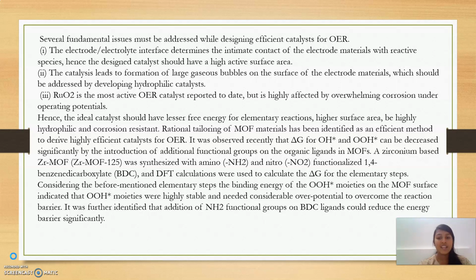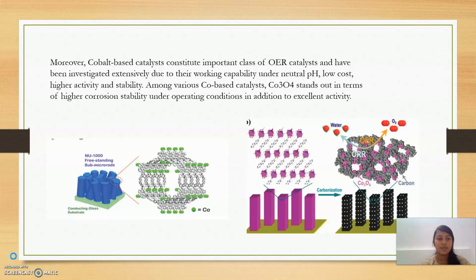It was observed recently that delta G for OH can be decreased significantly by the introduction of additional functional groups on the organic ligands in MOFs. A zirconium-based ZrMOF was synthesized with amino and nitro functionalized 1,4-benzene dicarboxylate, and DFT calculations were used to calculate delta G for the elementary steps. It was further identified that addition of amino functional groups on BDC ligands could reduce the energy barrier significantly.